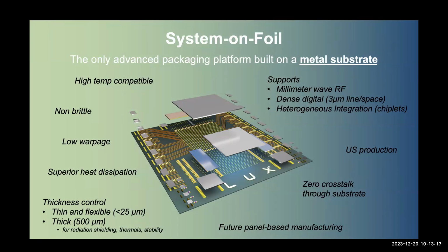Okay, so we're developing a technology that we call system on foil. The best way to think about it is it's just another material option in the world of advanced packaging. Typically, organics being the most common, silicon being the most common for advanced routing densities, and then glass kind of emerging as well. And so what we do is metal, and there's a number of high level benefits here: making it in the US, better for thermals. It's a relatively stiff material, so reduced warpage. We can also make these metal substrates very thin for flexible applications. But ultimately, it gets processed in a semiconductor fab. And so we're able to pattern high density and high fidelity copper interconnects on top and bottom of the metal substrate.